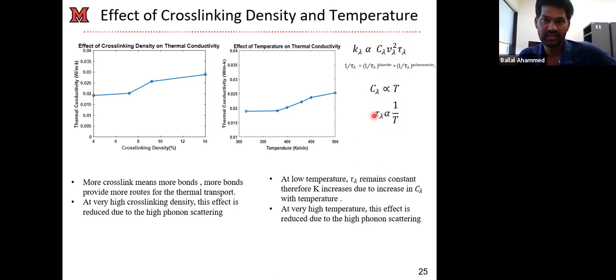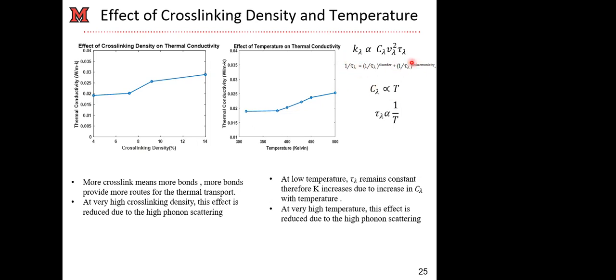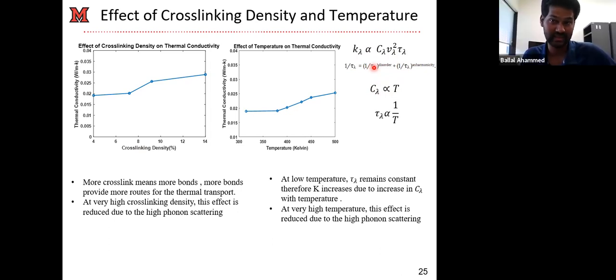And I'd like to mention that this relaxation time, actually, the 1 over relaxation time, is called the scattering rate for the phonon. This scattering rate comes from the disorder and the anharmonicity. In our case, our polymer is perfect, so it has no disorder and this term vanishes. So the main rate comes from the anharmonic contribution.